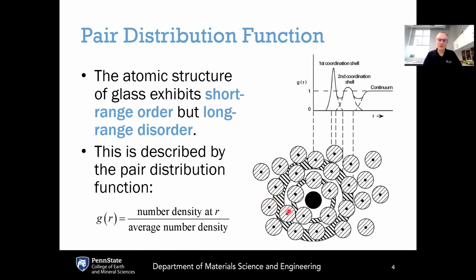And the way that the pair distribution function works is that if we have some material with some structure as shown here, where each one of these circles is an atom, and the dark smaller circles in the middle would represent the centers of each atom. To calculate the pair distribution function, we select one of these atoms as being the central atom. So in this case, the dark atom here in the center is represented as the central atom. If you go vertically up from here, this vertical dashed line corresponds to 0 on the r-axis. So this would be a radius of 0, which corresponds to the exact center of this particular atom in the middle.